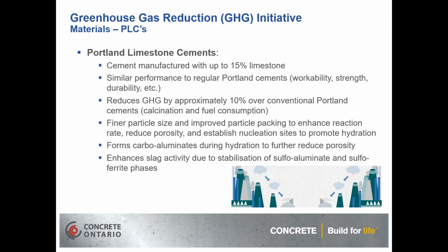So Portland limestone cements. These are cements manufactured with up to 15% interground limestone. And if you were on the last webinar that we had a couple months ago discussing Portland limestone cements, you'll find some more information about them. But basically, they are very similar in performance to the regular Portland cements. They have the same workability, the same strength characteristics, the same durability, and so forth. But we achieve about a 10% reduction in our carbon and other emissions with the Portland limestone cements.